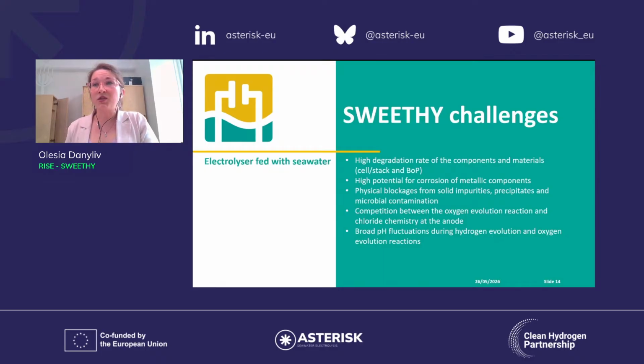What does it mean? It means that we will, of course, have a high degradation rate of components and materials in the cell and stack, and in the balance of plant. We will have high potential for corrosion of metallic components. We will have physical blockages because of solid impurities and microbial contamination. We will also have a competition on the anode between the oxygen evolution reaction and chloride chemistry. We'll have broad pH fluctuations during the hydrogen evolution and oxygen evolution reactions.